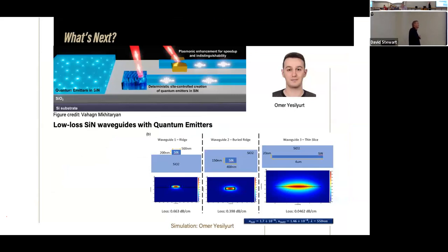So what specific things would we like to do next? We'd like to demonstrate a low-loss silicon nitride waveguide, somewhat different from what we've already done. It's known that if you do it in a symmetric configuration, specifically take silicon nitride and embed it in silica, and if you have it as thin as 20 nanometers, then loss could be remarkably low. Basically, the energy is still in the silica, but the structure is a very thin structure, much smaller than the wavelength, to just guide it for a long distance.